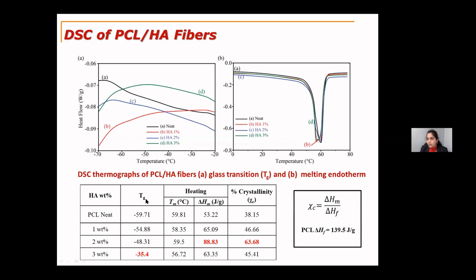But when we infuse these nanoparticles into the polymer solution, we can see that the glass transition temperature increased. With 1 weight percent, it improved up to -54. With 2 weight percent, it moved up to -48. And with 3 weight percent, it moved up to -35. So definitely infusing the nanoparticles changes the thermal properties of the material.